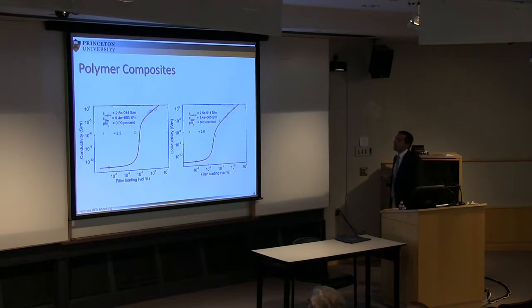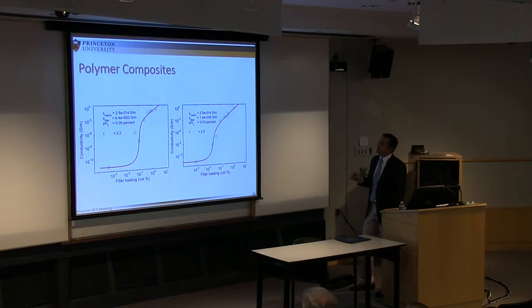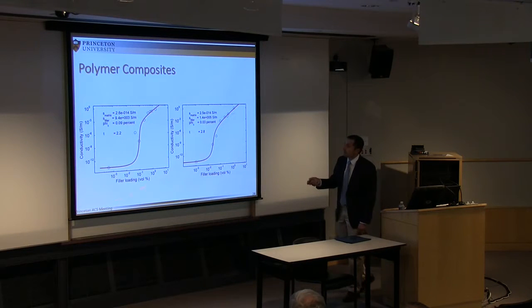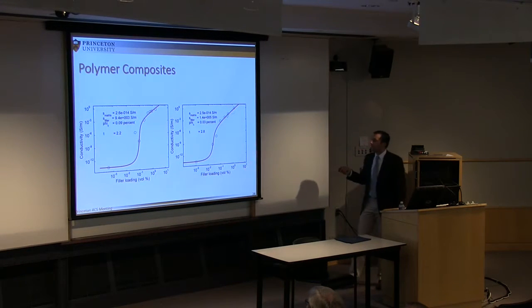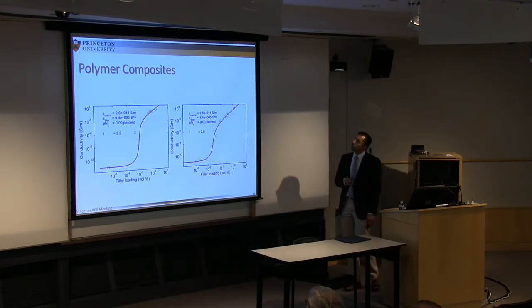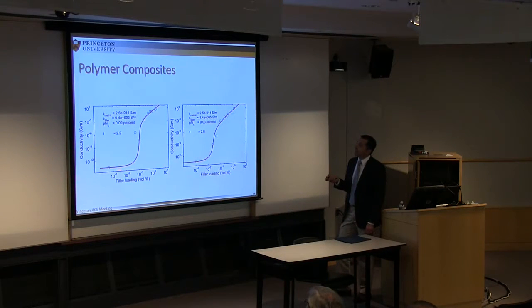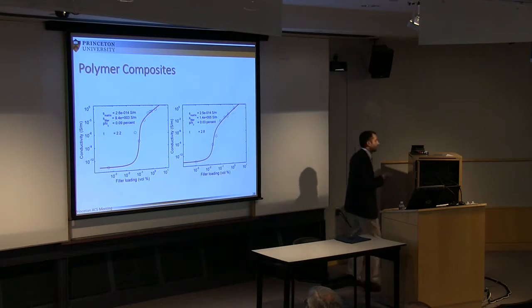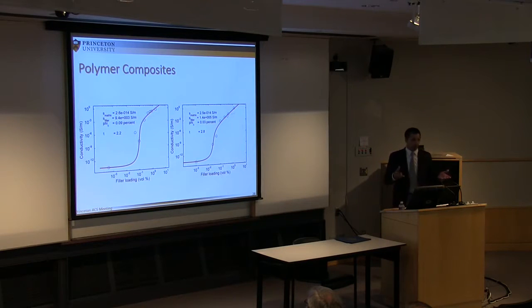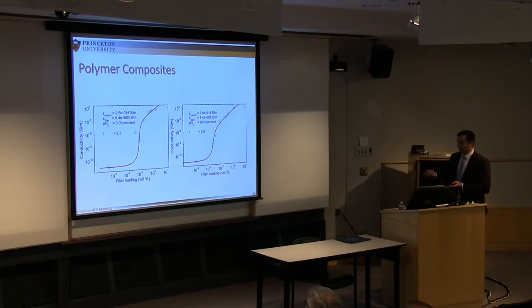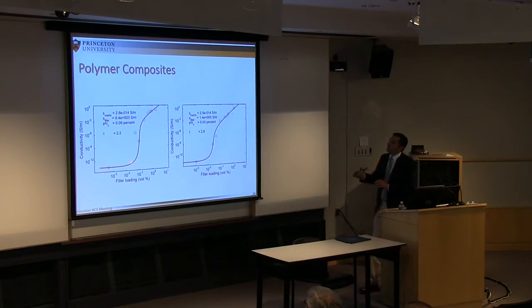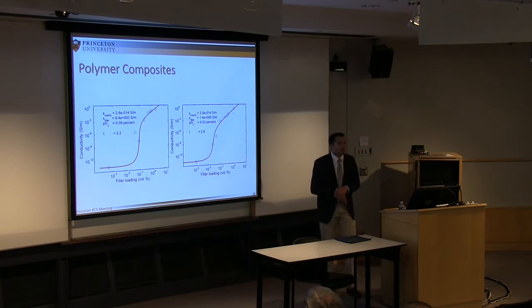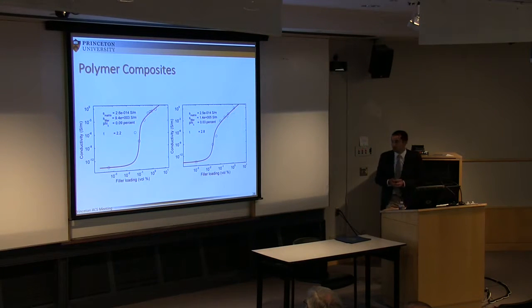So here we are looking at the conductivity of a polymer composite as a function of the carbon black loading here and graphene here, functionalized graphene. So you see that at the beginning, when you have a very small amount of graphene, the conductivity is about 10 to the minus 14, 13 Siemens per meter, which is the conductivity of the polymer. But as you reach a critical concentration, you have this sudden jump in the electrical conductivity. This is the percolation threshold.